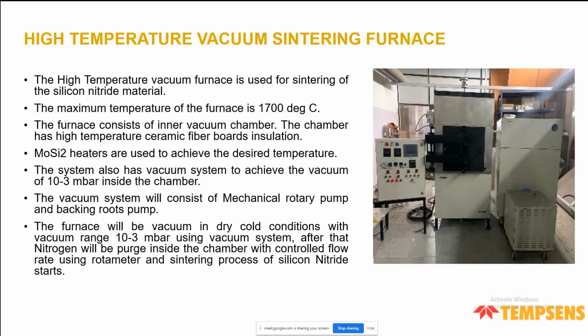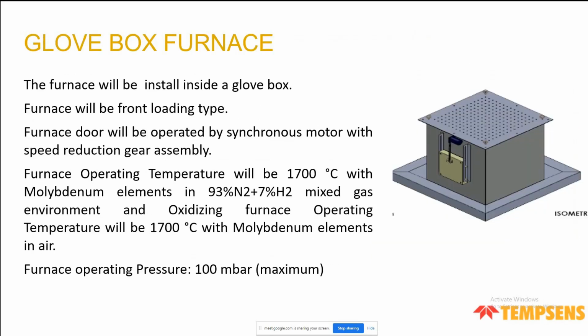for sintering of silicon nitride material. Temperature is up to 1700 degrees centigrade. It uses molybdenum disilicide, and also there are two vacuum pumps, a mechanical pump and a backing roots pump, and they are being used for the sintering of silicon nitride.